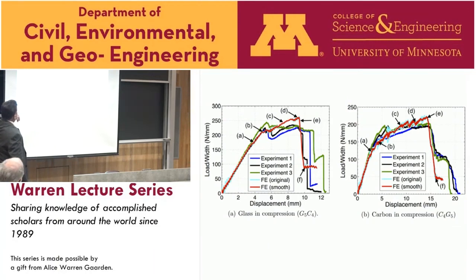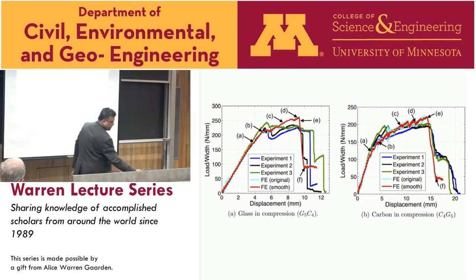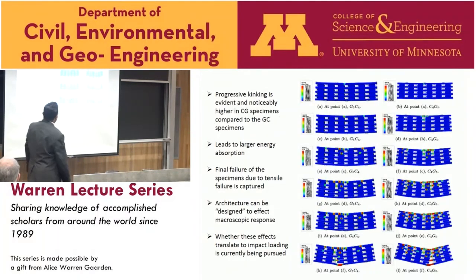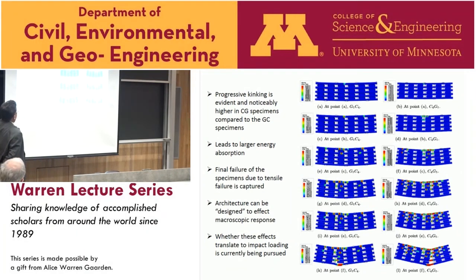What Dianyun says as FE original and FE smooth are the filtrations she did when she did the dynamic experiments. And you can see that when we change the glass on top and the carbon on top, the histories change, and you can see different behaviors. It's more dramatic in the next chart here, where glass is on the top, carbon on the bottom, and on the right-hand side, carbon on the top and glass in the bottom. You get progressive kinking much higher in the carbon on the top, glass on the bottom specimens compared to the reverse. A larger energy absorption or energy dissipation.